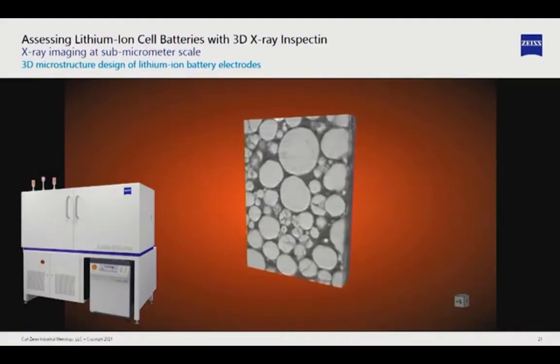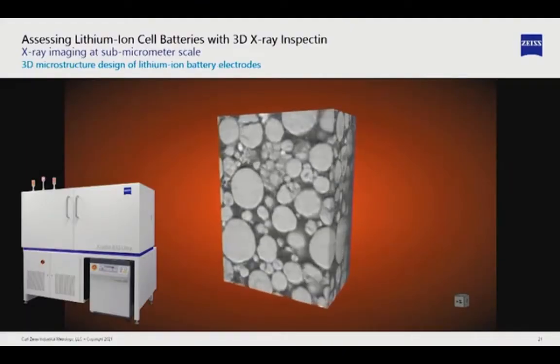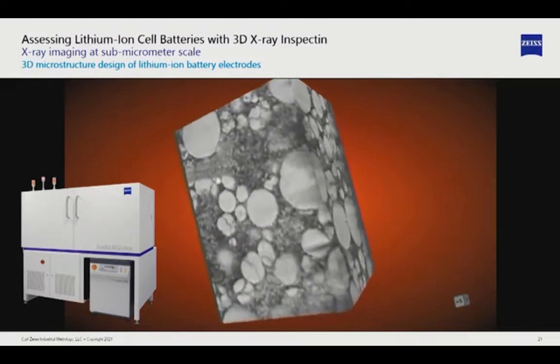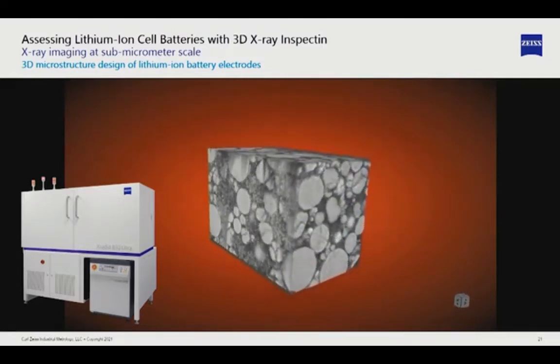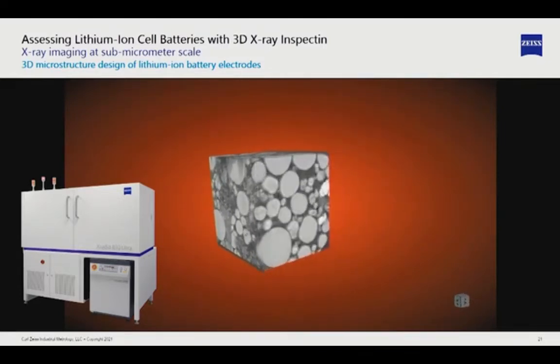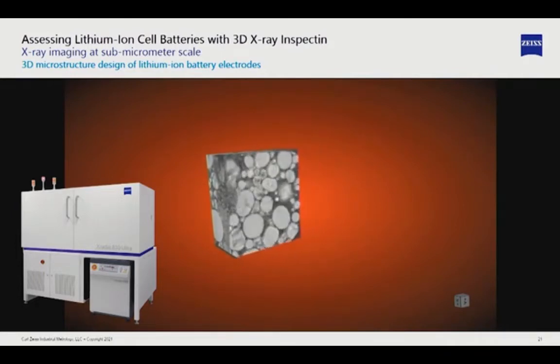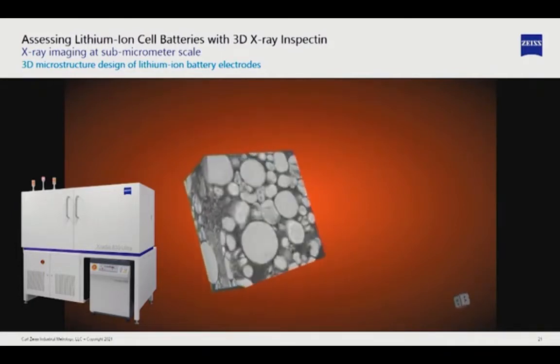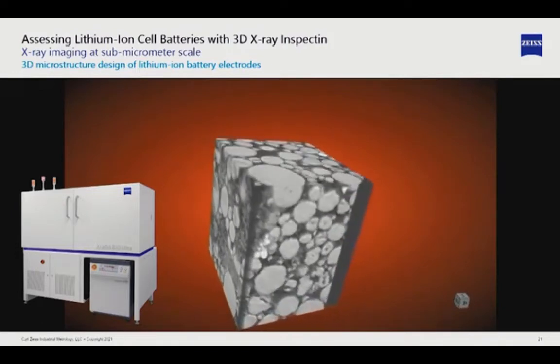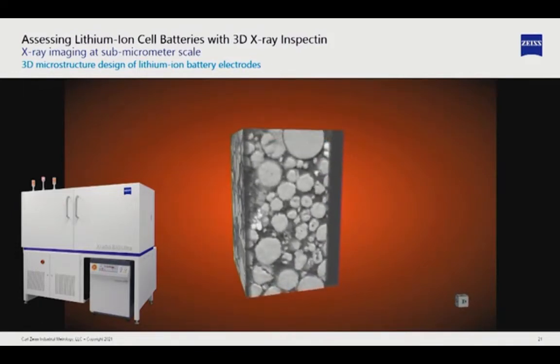And if we go all the way to the highest resolution that we can develop, which is down to 50 nanometers spatial resolution, with one of the best systems we have designed, you can see this level of imaging in which you even see small, very fine details in the particles. You can see that they are cracked, split in 2 or more pieces.